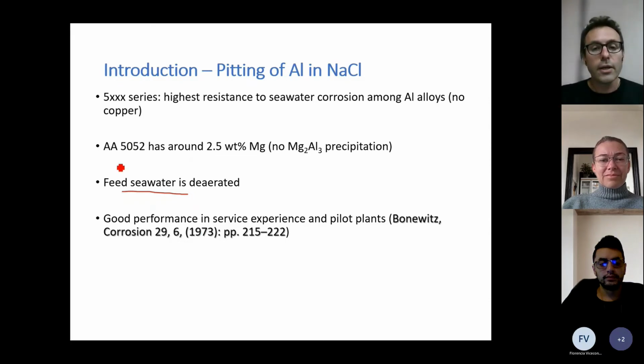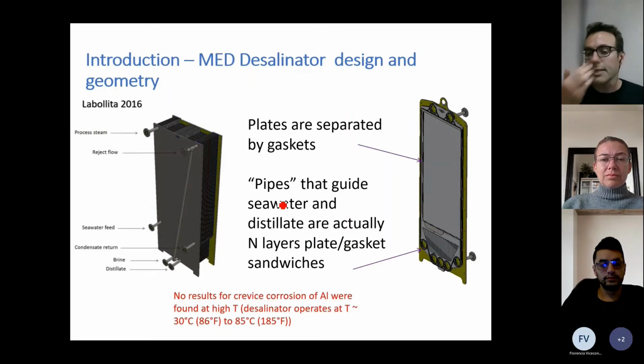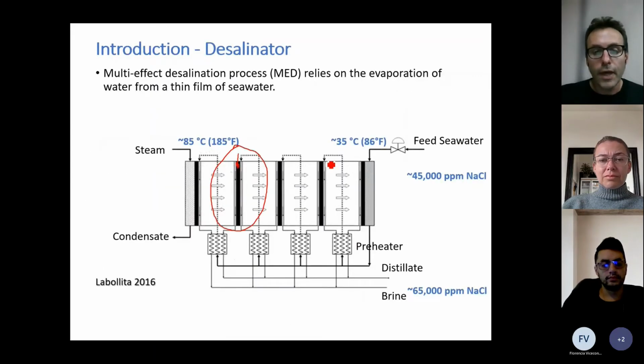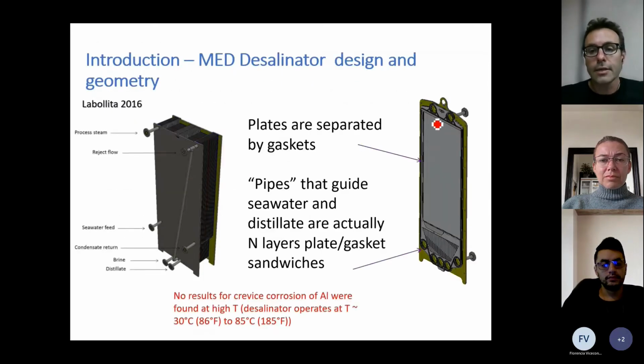And considering all these details of the material, the fact it doesn't have much magnesium, if you go to the literature, it has good performance in service experience and pilot plants. But the question still was, what about all the crevices that this desalinator will have, right? Because each one of those plates I mentioned in the first slide was connected to the other one by gaskets, right? And all those gaskets form crevices on the material. And when we went to the literature, we couldn't find any results for crevice corrosion of aluminum at high temperature.